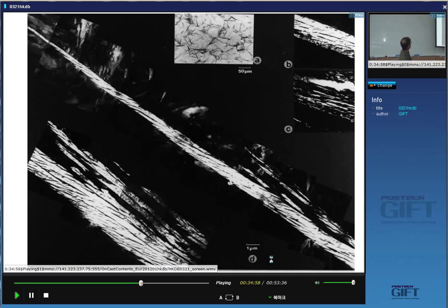The plate length over here is the same as the plate length over here. So they're all growing to a finite size because of this plastic accommodation. And that's very good for mechanical properties because you cannot get such a fine structure even with martensite. If this was elastically accommodated, then this would be a single plate. So we call this cluster of plates a sheaf of bainite. A sheaf is just a collection, just like when you harvest wheat. You don't hold individual strands, but you tie them up into a cluster, which is called a sheaf of wheat. This is a sheaf of bainite, S-H-E-A-F.